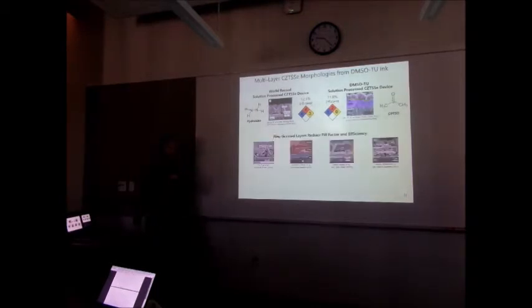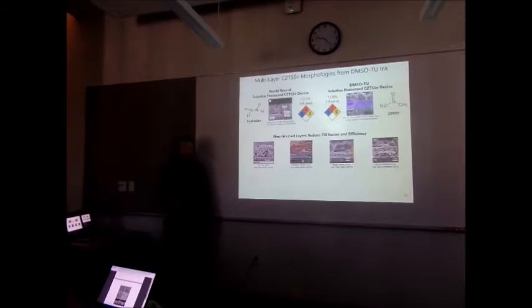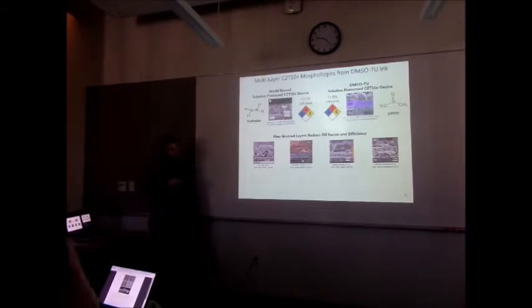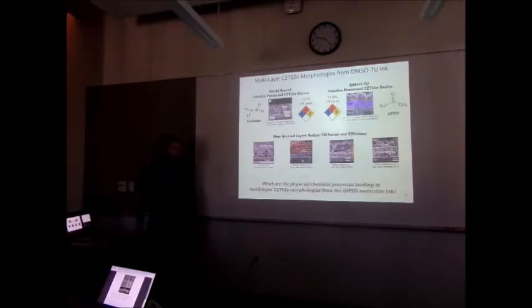A solution process that we developed in the Hillhouse group uses DMSO as a solvent, which is much more benign, much more non-toxic, and is nearly as efficient as these world record devices. The problem is that when other people in the literature have tried to reproduce this, they've gotten these fine-grained layers that reduce the fill factor and the efficiency of the device.